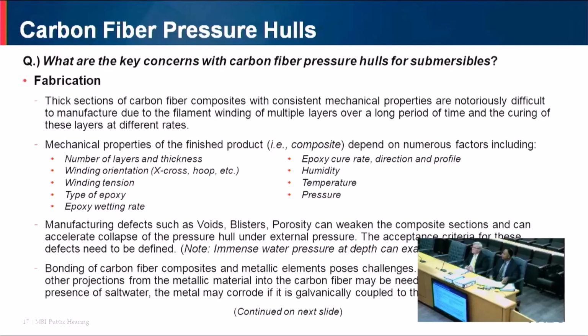Okay, so then the other aspect is manufacturing defects such as voids, porosity, blisters, and inclusions, which can have an effect on the strength of the carbon fiber composite. Voids are basically air pockets within the thickness of the carbon fiber composites. Blisters are formed on the surface of carbon fiber composites. Then you can have porosity. Porosity means a large number of voids in close proximity to each other. All of these can weaken the carbon fiber composite sections, and under extreme hydrostatic pressure, they can accelerate the collapse of the pressure hull.